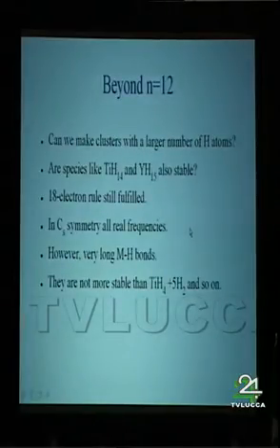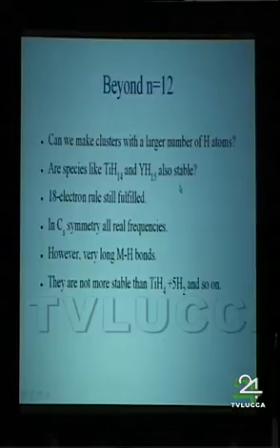So now the idea is, can we make clusters with more than 12 hydrogen atoms? Of course, the more, the better. So we ask ourselves if species like titanium H14 or yttrium H15 are also stable. All these species that we have looked at fulfill the 18-electron rule. So in principle, also titanium H14 and yttrium H15 should be stable. So we just ran calculations on these isolated molecules. They turn out to be local minima from the mathematical point of view, but they have very long metal-hydrogen bonds. And if you look at these simple energy balances, they are not more stable than the smaller clusters. So titanium H14 prefers to go to titanium H4 plus 5 H2 molecules.